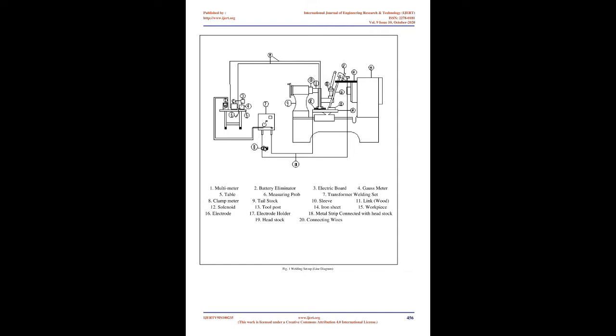The magnetic field exerts force on the electrons and ions within the arc, which causes the arc to be deflected away from the normal arc path. A transverse external magnetic field deflects the arc in the direction of welding, whereas a longitudinal external magnetic field deflects the arc perpendicular to the bead. Hughes and Waldock 8 saw that if unidirectional magnetic field is applied to an AC arc, or an alternating field is applied to a DC arc, then the arc can be oscillated in the position normal to the direction of welding. Recently, computer-aided artificial neural network, ANN, modeling has gained increased importance in the fields of materials joining. Some researchers like Dutta and Pratap 9 modeled the welding process applying conventional regression analysis and neural network-based approaches and found that the performance of ANN was better compared with that of the regression analysis.